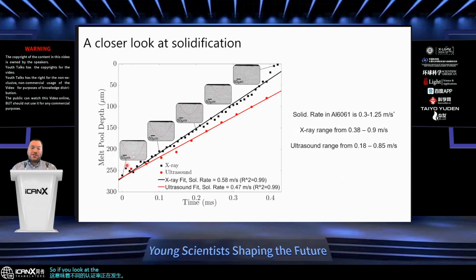So if we look at those slopes, the melt pool depth versus time, we can get solidification rates, which is an important parameter in how the microstructure forms. So our solidification rates from ultrasound is very much agreeable with what's recovered from the X-ray and what's in the literature.